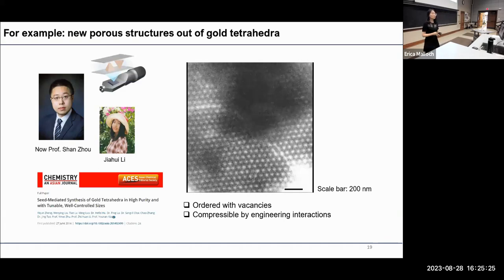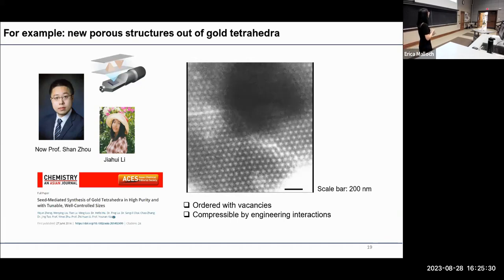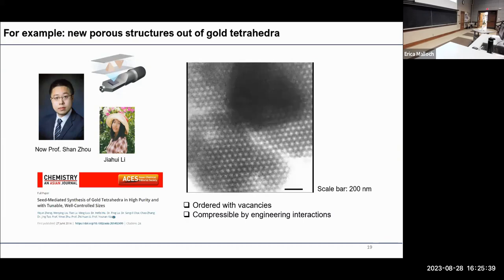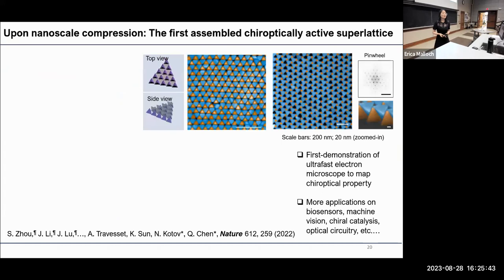So you can see, first of all, a beautiful lattice. But second, which is more important, you can also see a lot of voids in the lattice. Fundamentally, you will have voids because tetrahedron is a very special shape. It cannot continuously tessellate the three-dimensional space. And then what Shan and Jiahui were able to do innovatively is that first, they're able to reproduce the same porous lattice outside TEM on a silicon wafer, which is very important for property measurement and scale-up manufacturing.